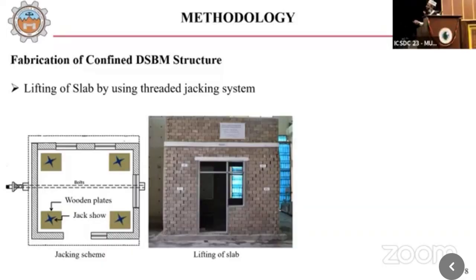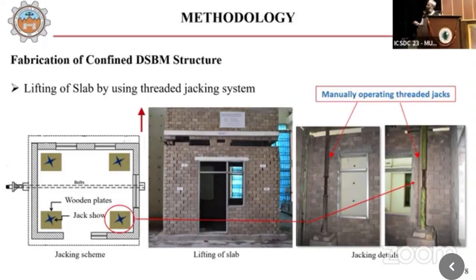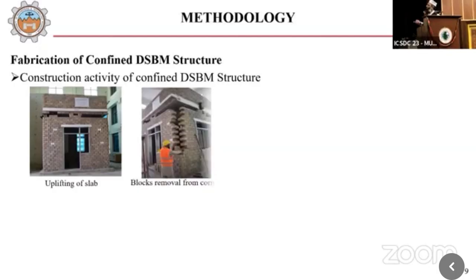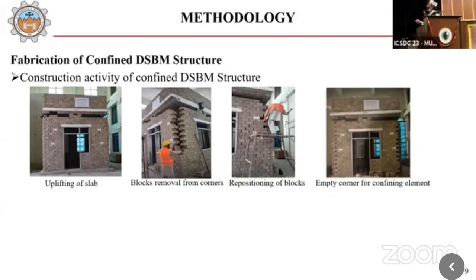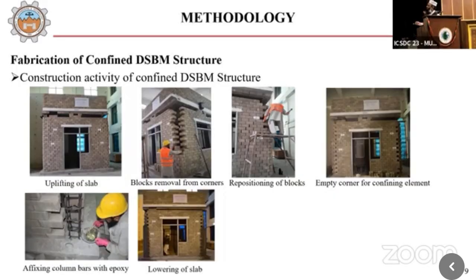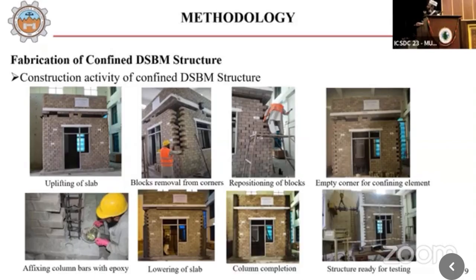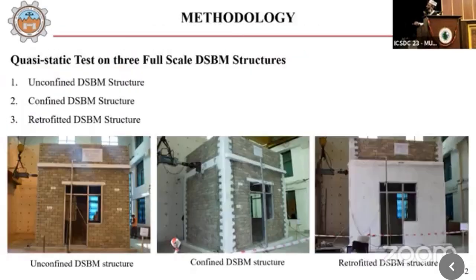After testing, you can see some cracks and bulging of these blocks. Now we know about retrofitting — how we can retrofit the structure. We lifted the slab with the help of jacking. Then we repositioned the corner elements, which are the confining elements. Here you can see the displaced blocks being repositioned and the empty corners for confining elements. This shows the affixing of steel bars for the confining elements, then lowering of the slab. After that, we retrofitted it with a ferrocement overlay.